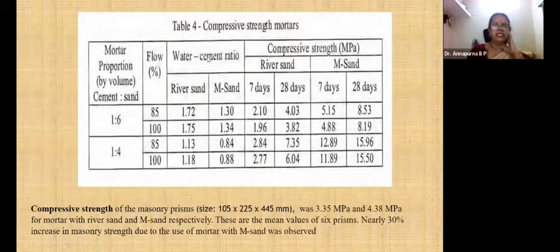Now, this is the strength of mortars which we have studied. For 1:6 and 1:4, the percentage flow here is 85 and 100, and here it is 85% and 100% for 1:4 also. When you see the river sand, the water cement ratio for 85% flow is 1.72, whereas for M sand it is 1.3, and for 100% also it is 1.7 and 1.3. But from this we can see that the water cement ratio of M sand is lesser than the river sand.